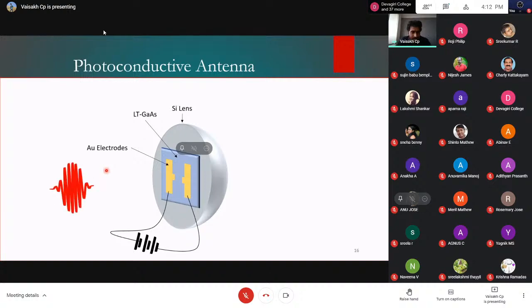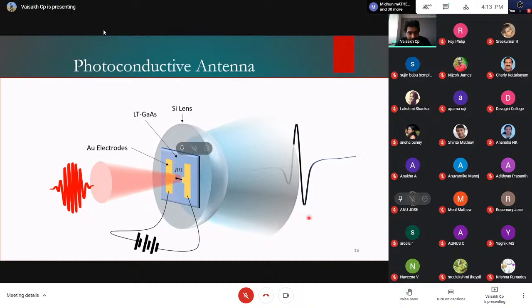When you excite this gap with a femtosecond pulse, you generate a large number of electron hole pairs here. Since the pulse is strong, it can create a large number of electron hole pairs. And now this is a conducting gap, and a current element appears here. But this current element does not stay there for long. It dies down very fast because of the choice of substrate we are using. Such current elements last for sub-picosecond time scales in a material like gallium arsenide. And what we get is terahertz radiation on the other side.